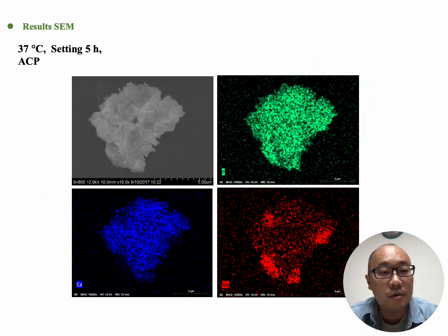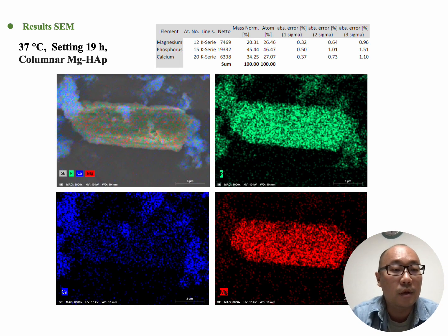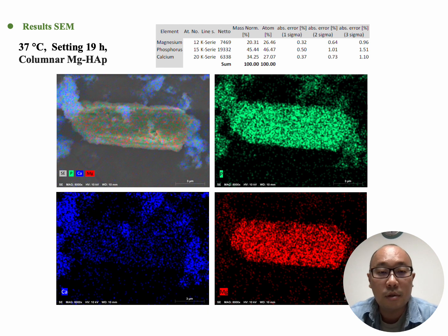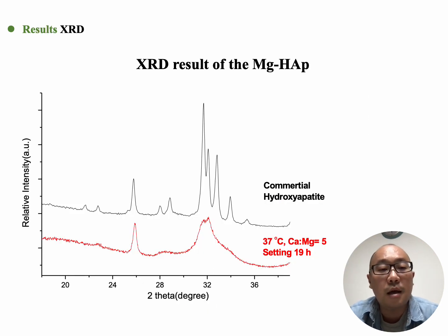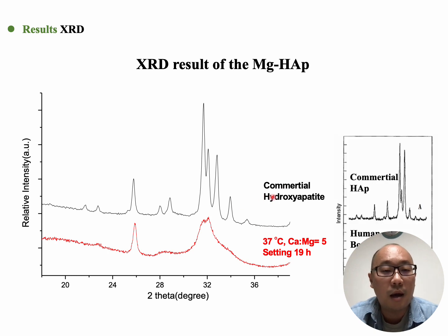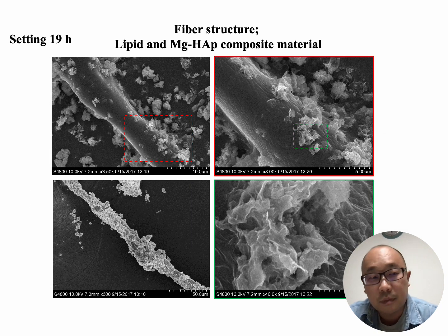So that's the EDS result. From the SEM of amorphous calcium phosphate, we can see lots of nanoparticles. And for the 19 hour, we can see some column-like structure. And the XRD shows the 5 hours is amorphous and the 19 hours is polycrystalline. And the commercial one is hydroxyapatite. It's similar to the human bone and the commercial hydroxyapatite. So let's look at the image from the SEM.